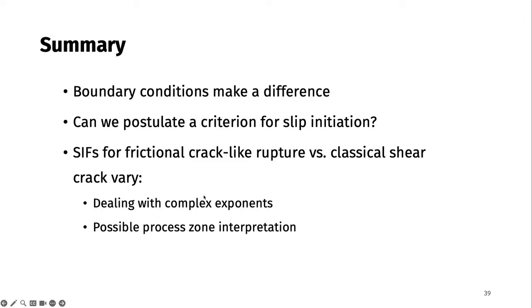The stress intensity factors, there is a technical problem. Again, I didn't want to get into these details, but for interface cracks, if you have worked out details for moving interface shear cracks, you will often see that the stress intensity factor has a complex exponent, right? And that is problematic because it gives something called an oscillatory stress ahead of the crack tip, which is unphysical because it leads to things penetrating and so on. That comes up in our model as well, the theoretical model.